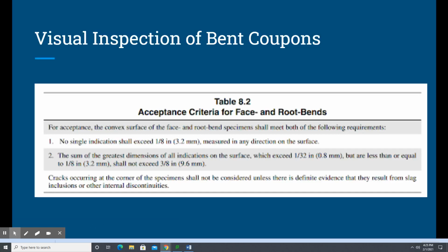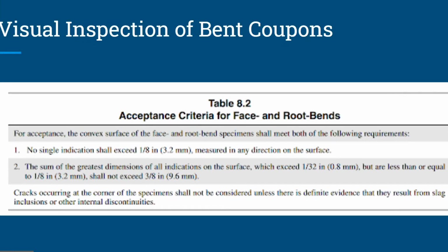And that's it. Back to the actual bend coupons. So different criteria. We're no longer looking at weld visual examination. We're looking at bend test criteria. So no single indication shall exceed 1/8 of an inch measured in any direction. So what we're looking at is any crack, any porosity, any slag inclusion, any defect in the weld, or I shouldn't say defect, any discontinuity in the weld bigger than 1/8 of an inch automatically becomes a defect and the bend fails. Okay. Now, if it's less than 1/8 of an inch, then we go to line 2.